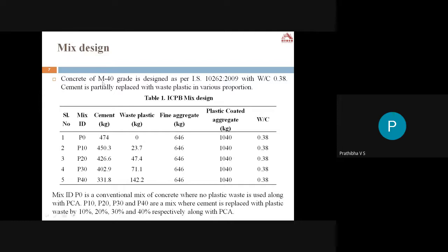As I said, we have used M40 grade concrete. The water cement ratio is 0.38. Here we have prepared 5 different mixes. P0 in the mix design represents the conventional concrete, whereas P10 means 10% replacement of plastic waste as a binder to the cement. P20 is 20% replacement of plastic waste for the cement, and P30 is 30%, and P40 is 40% replacement. Here the fine aggregate content will remain the same, whereas the coarse aggregate is completely replaced by PCA. So this is about the mix design.